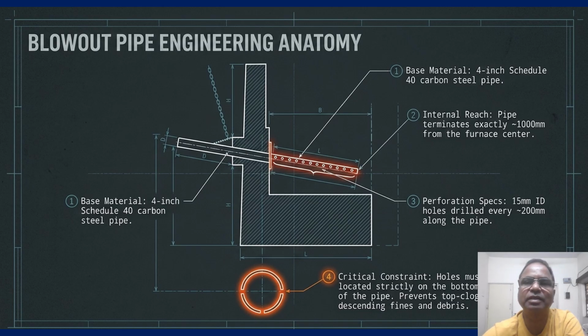So there is a critical constraint highlighted in orange. Those holes must be located strictly on the bottom and sides. Why? Because it prevents top clogging from descending fines and debris. If you drill holes on the top, the pipe will choke within hours.